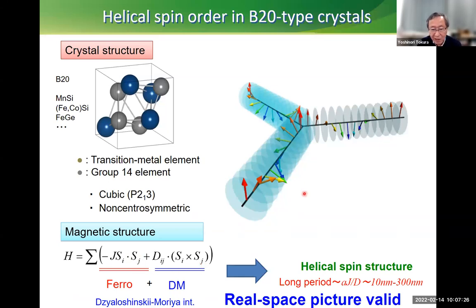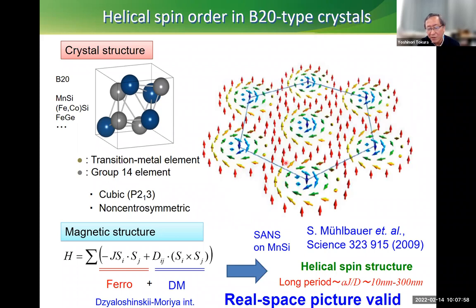This may form helical structures. The helical structure period is described by the competition between the J and D terms, and it's 10 nanometers to sometimes the sub-micron scale. And this defines some helical structures, Q structures. But under some conditions, it shows multiple Q structures. If you combine or hybridize these Q structures, then it shows a complicated two-dimensional spin structure. But if you scrutinize one unit, this is nothing but the skyrmion.